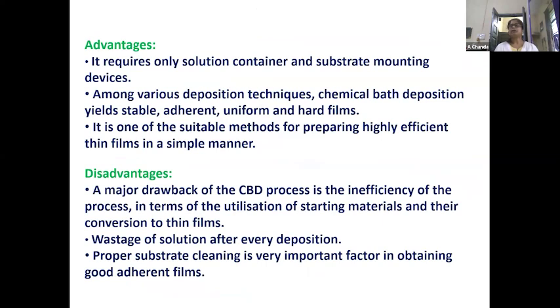And the major drawback of the CBD technique is the inefficiency of the process in terms of the utilization of starting materials and their conversion to thin films. That means whether the starting material, the precursor material we use, will be precipitated on the substrate surface or not. That is the main important drawback. And there is wastage of solution after every deposition. Substrate cleaning is a very important factor in obtaining good adherent films.